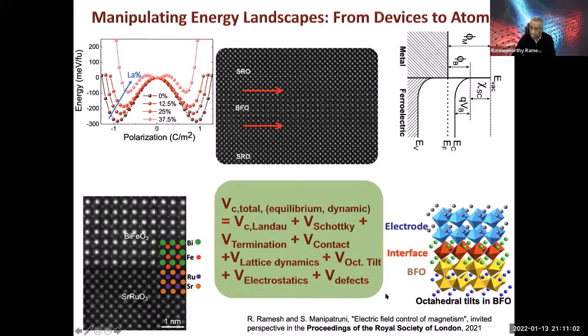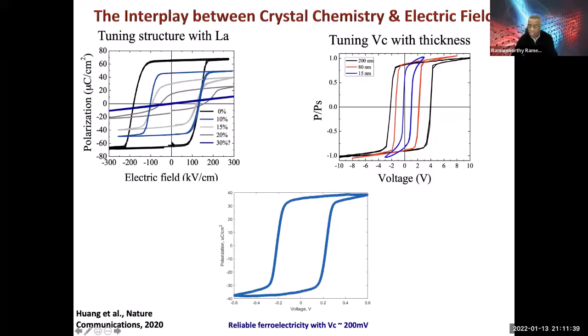So this green box summarizes everything that we're thinking about. The VC total is what you, as an electrical engineer, are going to be saying: I want to get to 100 millivolts. It's equilibrium versus dynamic. There is a frequency dispersion to the coercive field. That's composed of the Landau component, the Schottky barriers, if you have any, the termination effects, the contact resistance of the metal contacts, and lattice dynamics versus octahedral tilts. I will focus on this in the next slide because it's something that the ferroelectrics community has really not paid attention to.